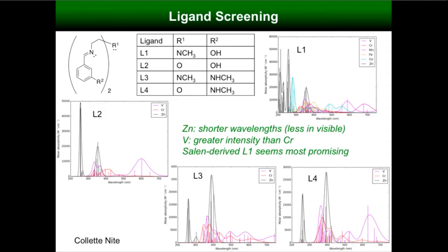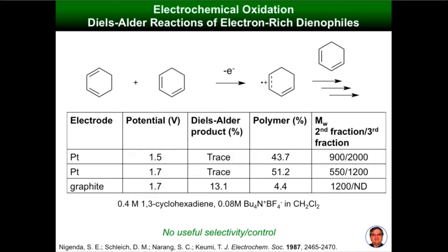So now looking at some selectivity. This reaction, which I talked about earlier, this dimerization of cyclohexadiene, if you carry out this reaction electrochemically, what people found a number of years ago was you make polymer. You don't do the Diels-Alder reaction. The overpotential needed for the chemistry is such that you don't make the right product.